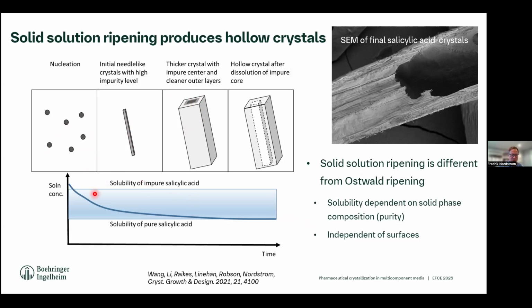So solubility is very high initially, and then it slowly drops down as the concentration goes down. And these impure cores then are, as you're approaching the equilibrium solubility of salicylic acid, whatever that is in this particular system, you are making the dirtier domains of the crystals undersaturated. And that means it starts to dissolve back in solution. So you're creating these hollow, kind of peculiar hollow crystals that form during this crystallization.